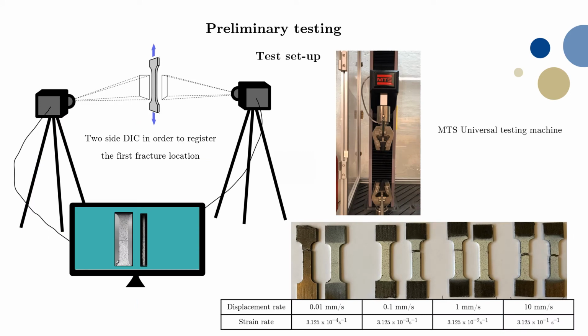The specimens were tested in a uniaxial MTS universal testing machine, and 8 specimens were tested. Each couple were tested at different strain rate from 0.01 millimeter per second up to 10 millimeter per second.